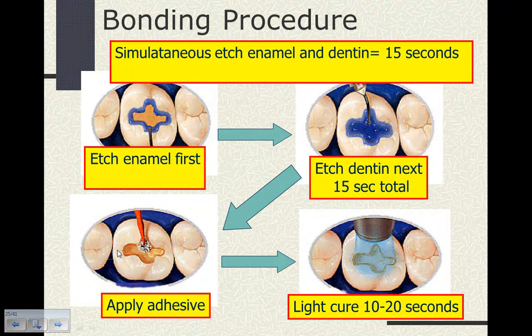Our bonding procedure is a simultaneous etch of the enamel and dentin for 15 seconds, where we apply the etchant to the enamel first. We then rinse and dry the etchant out of the tooth, apply our adhesive to the etched enamel and dentin surfaces, evaporate off the solvent, and then we light cure for 10 to 20 seconds with the light at right angles and as close to the tooth structure as possible.